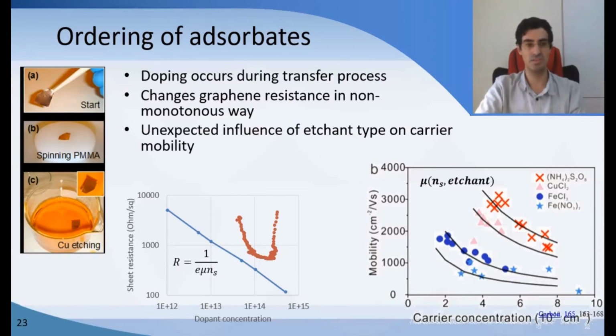The other thing that we're seeing is that, even if we're keeping the same number of charges and the same amount of charge transfer, depending on the etchant that we're introducing, we get different mobilities at the same concentration. This is strange because up till now we always assumed that charge transfer was the only thing that would introduce scattering, but now we see that there seems to be another quality of charge transfer, depending on the chemical, that has an effect on mobility.